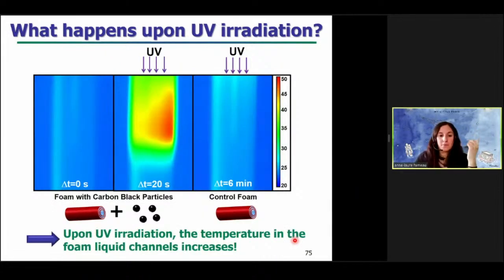But what is happening? To understand what is really happening, we used an infrared camera to record the evolution of the temperature inside the foam upon UV radiation. So here on this picture, you can see that the temperature of the initial foam was around 25 degrees. And for the foam with the tubes and the carbon black particles, we can see that after 20 seconds of UV irradiation from the top, the temperature inside the liquid foam channel increased to around 45-50 degrees. That is to say, above the temperature transition from tubes to micelles for the system that we chose for this study. And for the control foam just with tubes, even after 6 minutes of UV radiation, the temperature of the foam remains almost constant around 25 degrees. So really, upon UV radiation, we can clearly see that the temperature inside the foam liquid channel increases due to the presence of these carbon black particles.